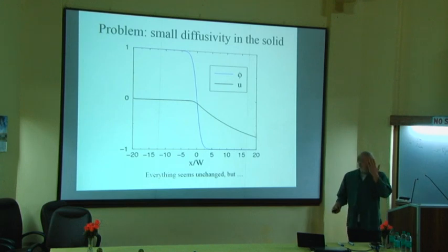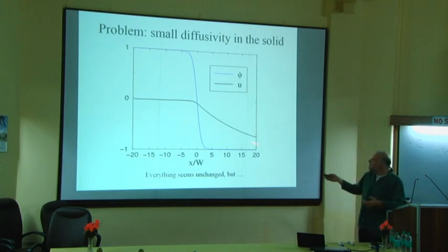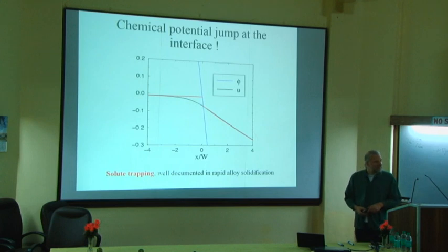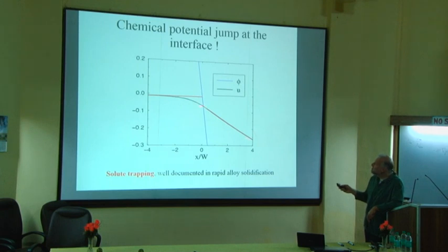So if you remember yesterday's graph, the profile looks fairly similar. But if I repeat now the same procedure as yesterday, that is, I fit an asymptote here and I fit an asymptote here, what do I get? Here's the picture. So you see the two ends do not have the same intersection point with the interface. Okay?